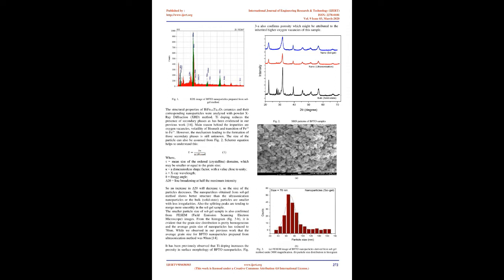The nominal composition of Bi0.9Ti0.1FeO3, BFTO, bulk polycrystalline materials were also synthesized by a conventional solid-state reaction technique, and by using ultrasonication technique corresponding nanoparticles were produced directly from their bulk powder materials. Characterization. To observe the crystal structure of the bulk, the pellets were ground into fine powders while the nanoparticles needed no additional measure. The structural properties and phases present in the crystalline samples were determined from the XRD patterns given by the X-ray diffractometer, Bruker D8, Cu Kα1 radiation,